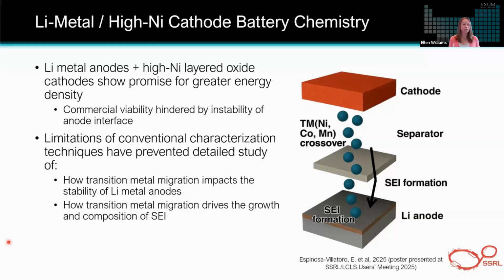Source. And for those of you who are familiar with this facility, you know that as part of the synchrotron, they have a ton of very powerful analytical techniques, most of which are X-ray based, that have a lot of powerful abilities on morphology and transition metal analysis. A lot of work has been done on this specific chemistry type on the transition metal migration. But what those techniques struggle with is reliably measuring lithium. And so that's where our LALI TOF-MS technique very well complements all of these capabilities at SSRL.